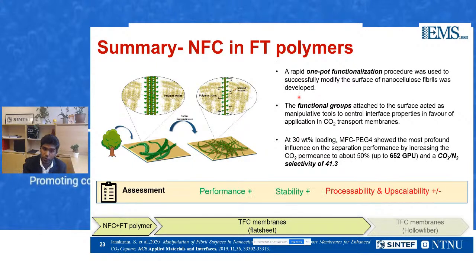When you check the assessment of these membranes, the performance was very good, and the stability was also very good because we were able to make these membranes into 300 nanometer selective layers, and they were performing quite well. However, we did not see upscalability being on the positive side. The reason is that the functionalization itself is a very expensive procedure, because we want to attach PEG molecules onto cellulose. The second thing is that we are loading up to 30% of this functionalized material into the polymer, which is quite a lot of loading for achieving such a small, 50% increase with respect to CO2.